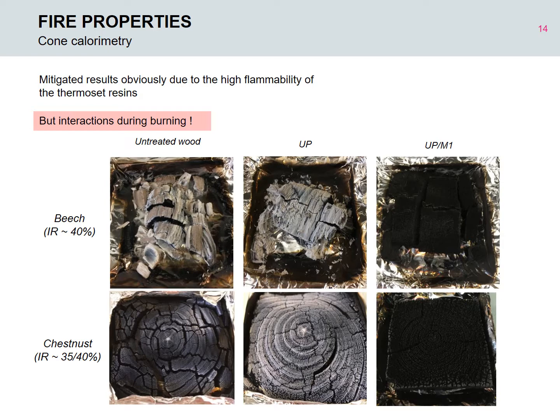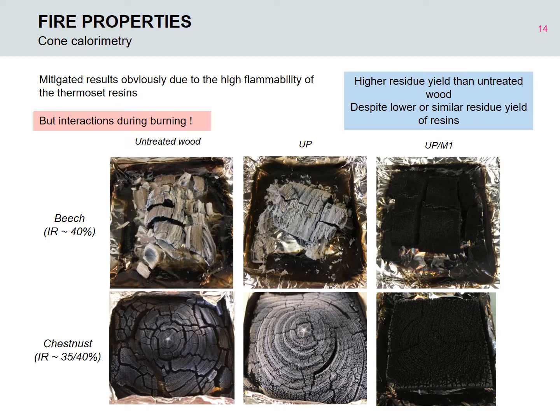Despite these disappointing results, there are some other comments to make, especially about the charring. Here you can observe pictures of the residue at the end of the cone calorimeter test for untreated wood and wood plastic composites. For the composites containing phosphorus, the residue is black. It contains a high amount of char, and a main observation is that despite a lower or similar residue of resins in comparison to wood at micro scale, in cone calorimeter, the residue content of wood plastic composites is much higher than wood. It means that there are some interactions during burning, and probably phosphorus improves the charring of wood and also improves its thermal stability.